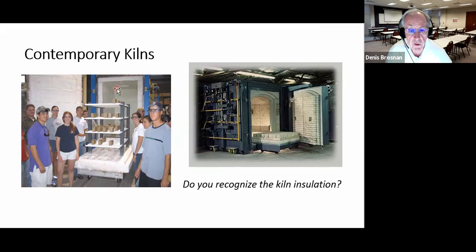I can tell from looking at this that this kiln has a temperature limit of around 3,000 degrees Fahrenheit, just from the fact that most of the fiber will shrink appreciably when you get above 2,900 degrees Fahrenheit or thereabouts, and get into the realm of 1,400 to 1,500 degrees Celsius.